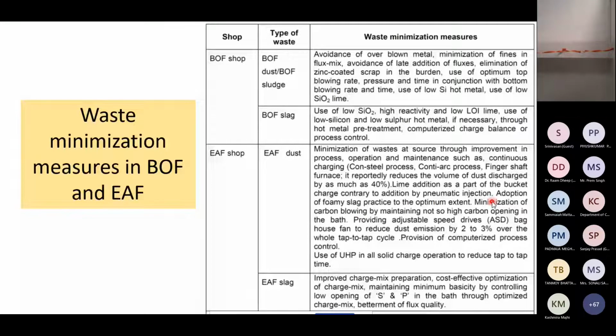When the bucket is charged with the coal and ore, with that only lime should be added, properly mixed and added; separate addition is not required. Adoption of foamy slag practices to the optimum extent, minimizing the carbon blowing by maintaining not so high carbon opening in the bath, providing adjustable speed drives, ASDs, for the baghouse fan to reduce dust emission by 2 to 3%. So there are various measures by which we can reduce the waste, particularly the solid waste which is generated from this process.